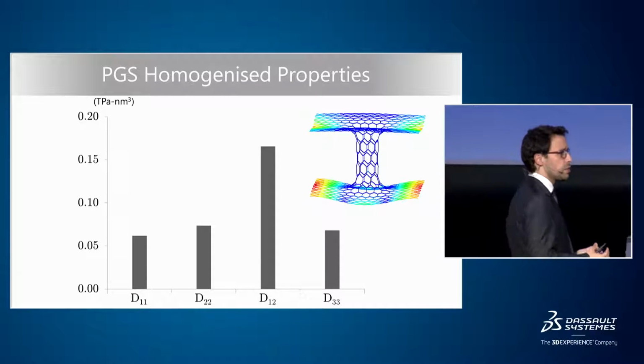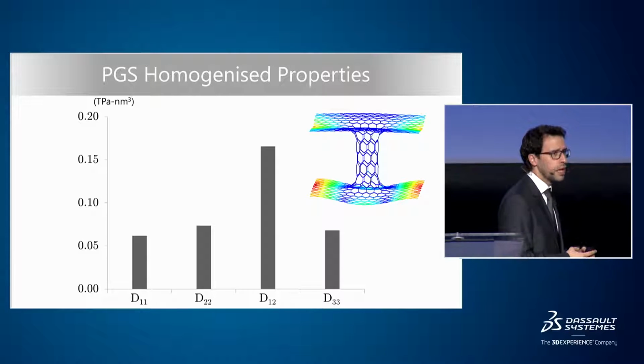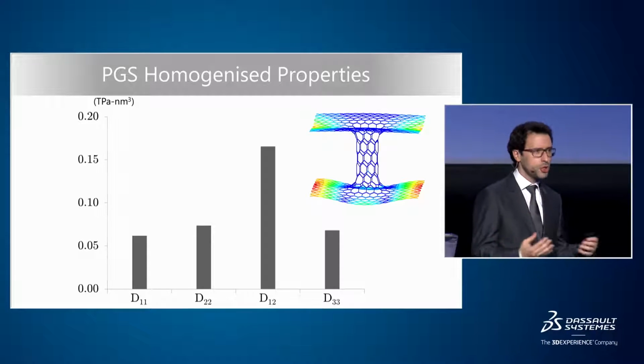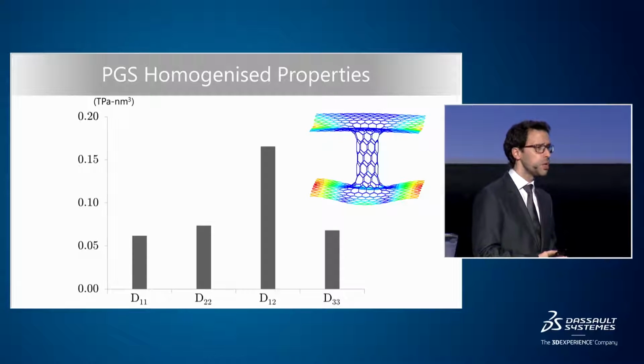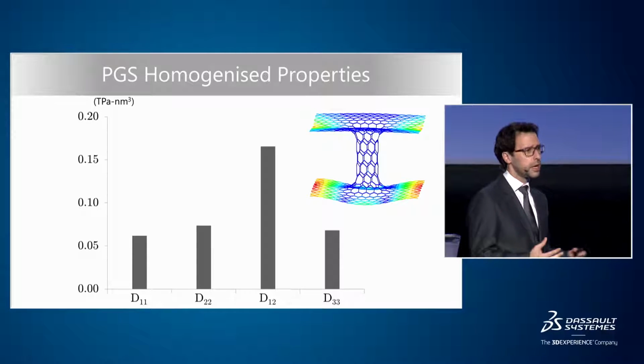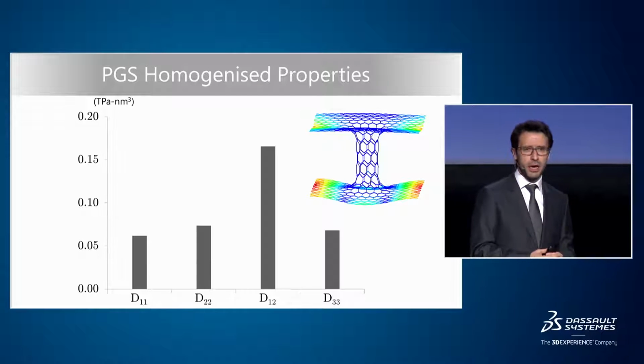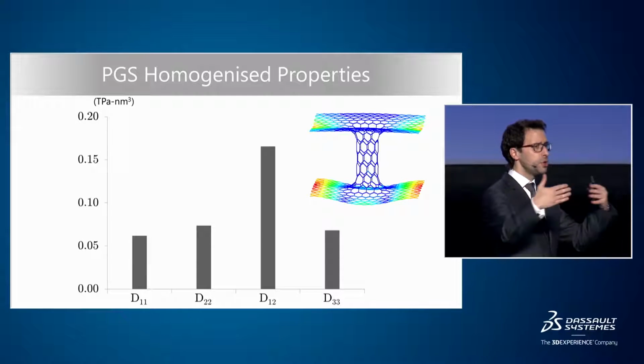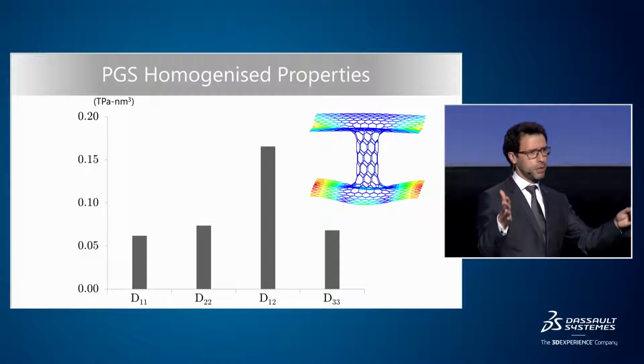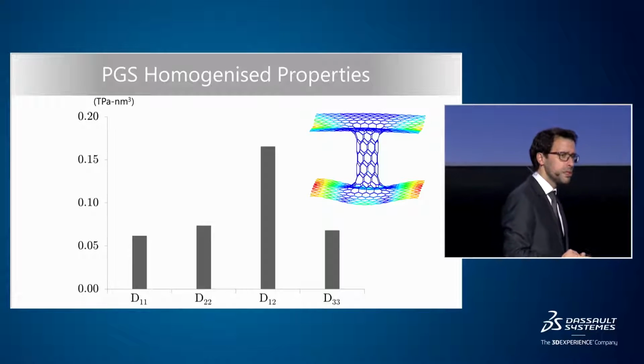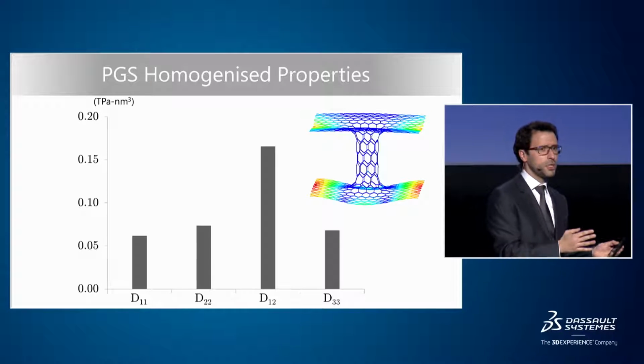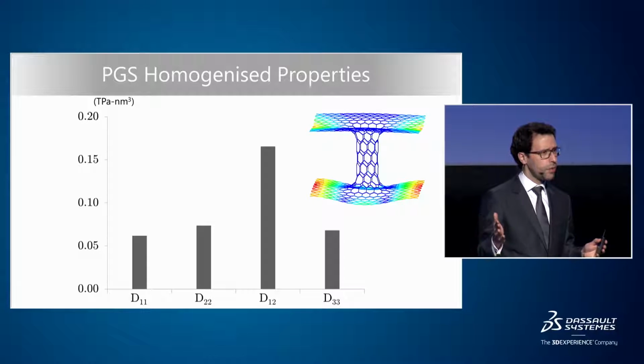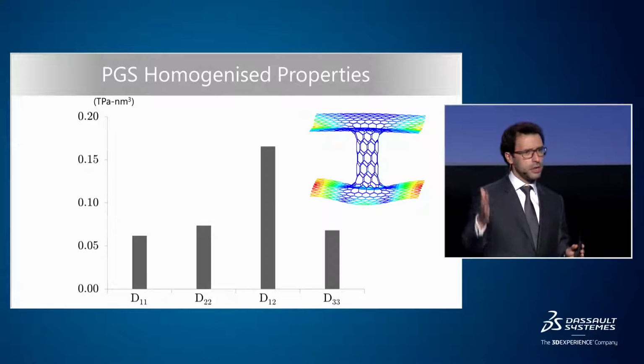Now, the reason we are doing this is because we want to be able to simulate relatively large problems. And for this, one of the things we want to do is to be able to homogenize the properties of our material. Now, typically in continuum mechanics, when you want to obtain homogenized properties, you create a unit cell model and apply periodic boundary conditions at the sides of that unit cell model. With molecular dynamics, it's a bit more difficult because your physics is non-local. You have long-range interactions, so you cannot simply cut the boundary and apply something at the boundary.